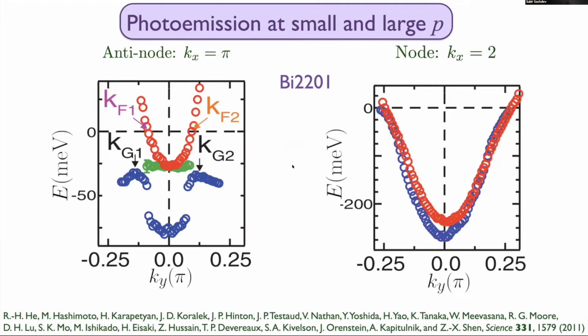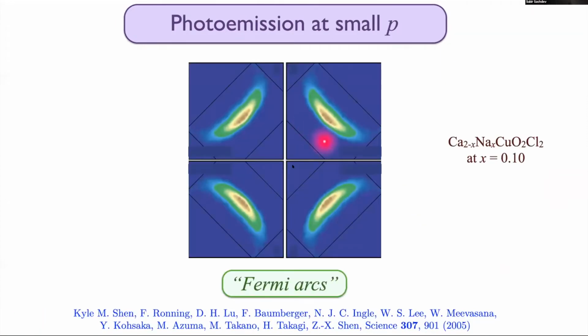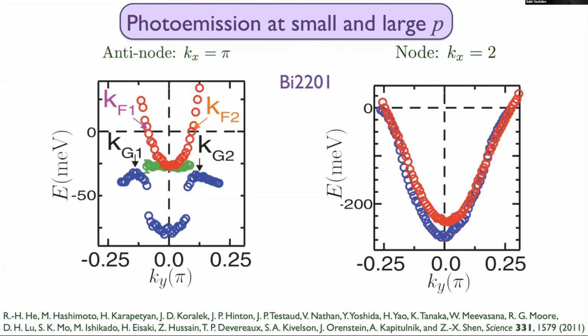Okay. And I'll tell you how we think about this. Also, if you look on the antinodal side, on the nodal point, this here is a scan, I think, somewhere here through the nodes. And there you get a Fermi surface crossing. And there's hardly any difference between the overdoped and the underdoped side. They're pretty much the same. And in fact, that's an issue with the pair density wave model that gives you all kinds of bizarre structures near the nodal regime.